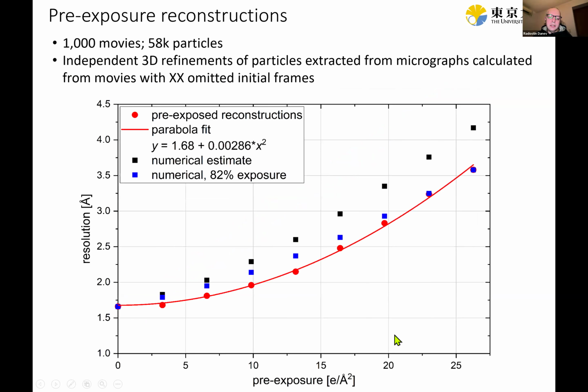So here you see on the horizontal axis the pre-exposure to the sample, and then the resolution on the vertical one. The red dots represent the results, and this data was fit very well by just a parabola. I also did some theoretical estimation of what the resolution would be based on an empirical damage model by Nikolaus Grigorieff and Tim Grant. And the black points here are the simulation using the same exposure that was measured in the experiment. By adjusting the exposure, reducing it to 82% of the experimental exposure, it got much closer to the simulated one. So I'm not sure if the measured exposure is not accurate, or the empirical model is a little bit off.